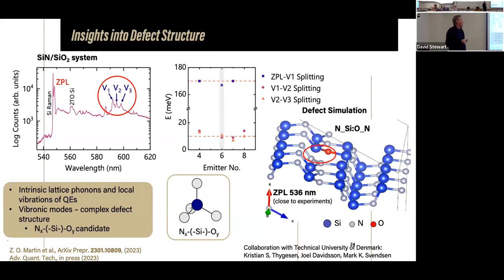And for this type of defect, what is predicted is that you would have these vibronic modes, V1, V2, V3. And what we observe experimentally, going from one emitter to another, is that the separation of this group of peaks from the zero phonon line is around 170 and stays so. Whereas the separation between these particular peaks is around 10 meV, and it stays so when you move from one emitter to another. So it looks like that's exactly the nature of this emitter, which we create by applying strain, remember, when we do this rapid thermal annealing.